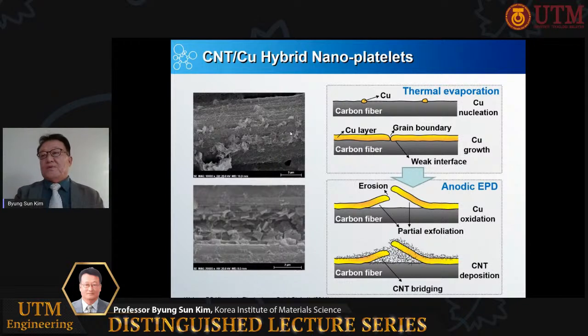Carbon nanotube reinforced copper nanoplatelets were developed by a simple two-step deposition method. They are thermal vapor deposition of copper and anodic electrophoretic deposition of CNT. Due to the fast corrosion during the electrophoresis, the copper layer is broken into pieces and exfoliated to form platelet structures. Then during the EPD process, the CNT deposition will bridge the gaps. Consequently, highly conductive and strong CNT copper nanoplatelets are effectively built up. When applied in carbon fiber composite, the CNT copper nanoplatelets significantly enhanced both interlaminar shear strength and electrical conductivity compared to baseline composites.